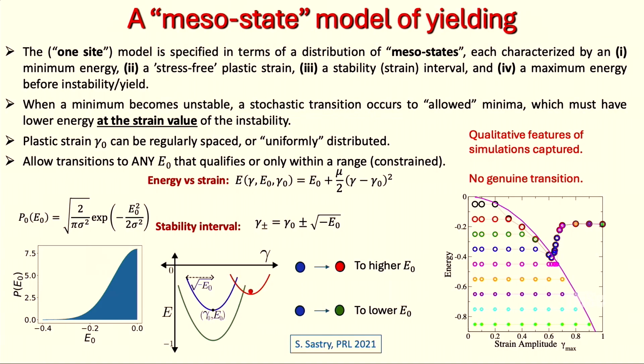So this is an energy landscape picture of an individual mesoscale block. I can think of the system residing in different what we call mesostates, which have different energy in a stress-free condition, and then I can change the strain so that the energy goes up quadratically with the strain, and at some point I'll reach a limit of stability, and this limit of stability I choose to be proportional to the square root of the depth. When you reach the limit of stability, you hop into another minimum. That other minimum under athermal conditions would have to be a new mesostate which has at that strain a lower energy.